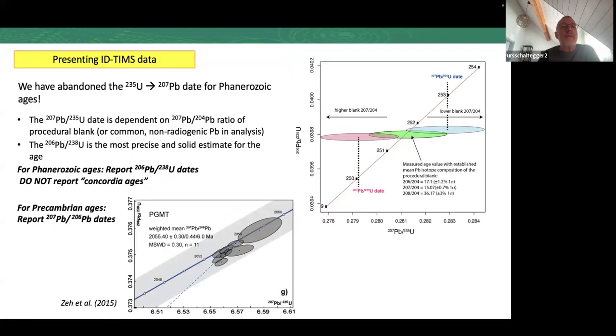One word on the presentation. We have abandoned the 235 uranium to 207 lead decay, at least for Phanerozoic ages. Why? Look at this green ellipse here. This is a real measurement we have done, and it has been corrected for the procedural blank with our average of the blank composition we have in our lab in Geneva. But of course, this is a series of measurements, so we have to add an uncertainty to these values. And when we now shift this ellipse within these uncertainties, we can easily make it inversely discordant or normally discordant. That means the 207-235 date is actually not significant anymore. It could be 250 or it could be 253. That means we abandon this date.